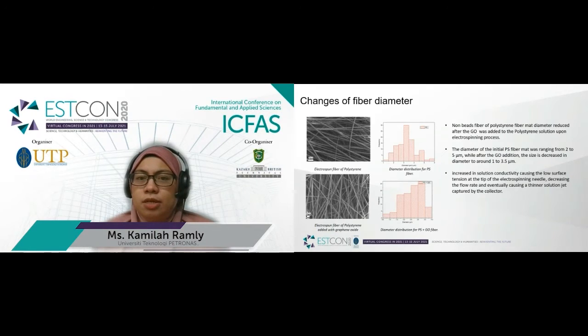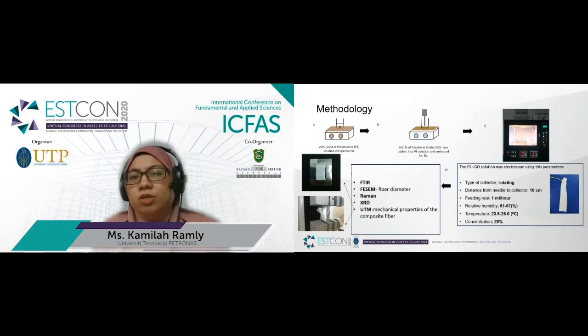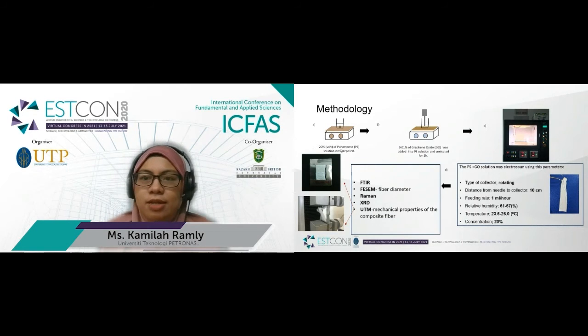For a start, polystyrene solution was prepared at 20% weight over volume in dimethylformamide. It was stirred for 12 hours to promote a homogeneous mixture. Graphene oxide in water dispersion was dried at 80 degrees Celsius for 12 hours to eliminate water content in the graphene oxide prior to the electrospinning process. Afterwards, 0.01% of graphene oxide was added to the polystyrene solution and sonicated for 1 hour to promote homogeneous dispersion.